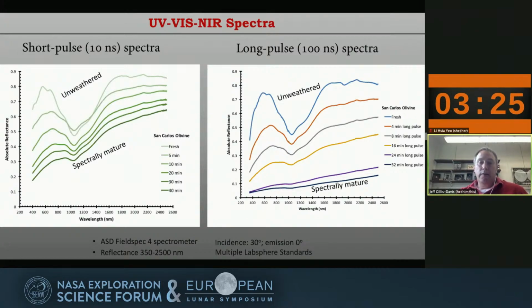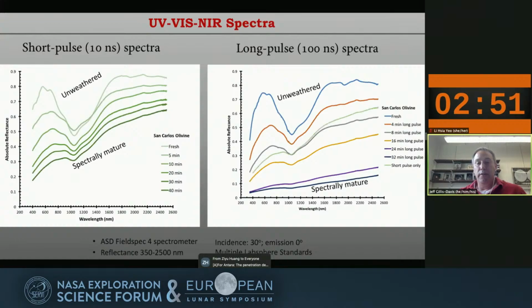On the right are our long pulse spectra. Again, this is San Carlos olivine. And as you can see, as we move to lower albedo, at our longer duration of long pulse, at 32 minutes, we have made a spectrally mature material where the 1 micron band is essentially erased. It is definitely flatter, or what you may call bluer, than the short pulse laser weathering measurements, and it is definitely a lot darker and more closely matches lunar materials that have been space weathered. And just for comparison, I popped up the green line. The short pulse laser shows where we are at the maximum amount of laser space weathering with short pulse, versus the intermediate amount for long pulse weathering.